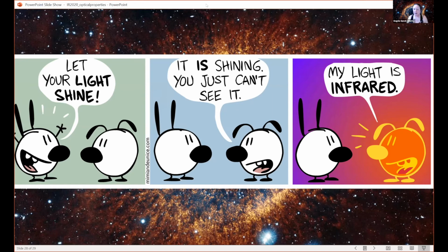And you're actually going to need to have samples of different thicknesses. So remember, it's a slab, but you want it to be transparent enough to have some light go through so you can measure it, but not so transparent that you don't get any absorption. So you have to get the thicknesses in the right range, and that's going to be different in the ultraviolet than it is in the infrared. So what you want is a sample that is big enough that you can basically slice it up into pieces.